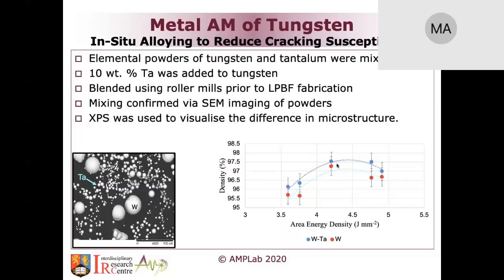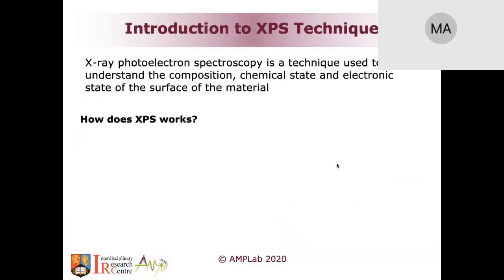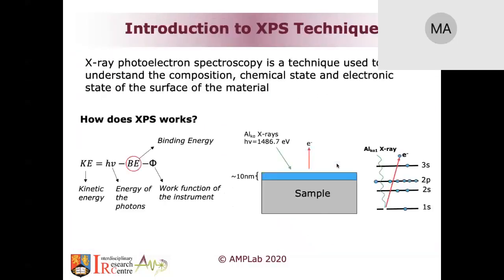But to try to understand what actually happened, we needed to use XPS, X-ray photoelectron spectroscopy, to look into what happens in the microstructure. For those of you who don't do XPS, I just put a slide to explain it. It's a technique used to understand the composition of the surface of the material, because we wanted to know how they differ, what the microstructural difference between the two would be. The way it works is that X-rays are directed onto the surface of the sample, and you get characteristic electrons out of it, which give us an indication about the surface condition, the type of elements present, and the chemical state on the surface of the material.